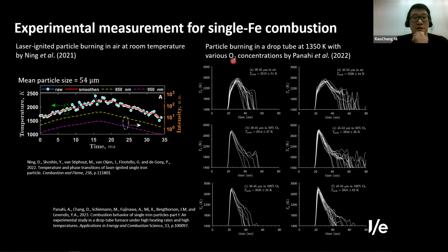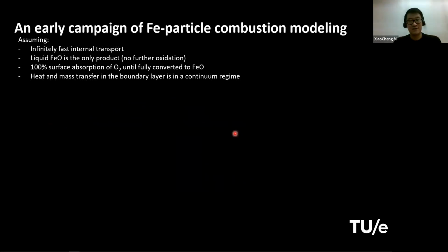And these are some results obtained from the drop tube experiments. These authors performed two sets of particle sizes, although not very far apart: 38 to 45 micron, and 45 to 53 micron. And they did this in three different oxygen concentrations. The top one is in air, the middle one is in 50% oxygen, and the bottom ones are in 100% oxygen.